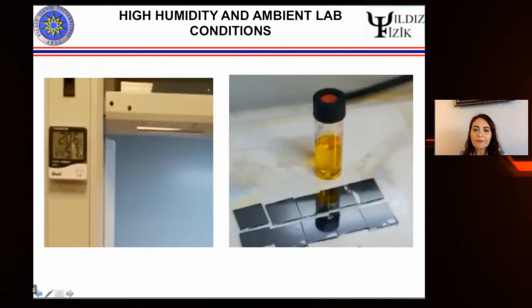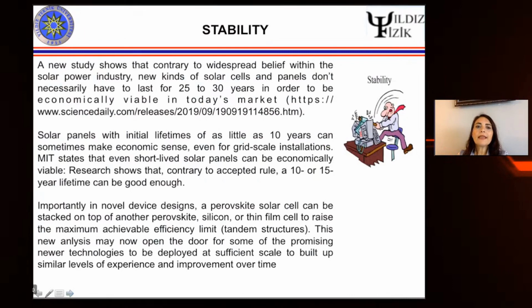So you see, in the previous talk, we also heard about these shiny, mirror-like perovskite layers, and this is high humidity conditions, and this is ambient lab condition, and these are our perovskites. What about the stability? Yes, stability is an issue, but there was a study like this. It was trying to say that people are expecting 25 years of lifetime, because this was the one which was provided by the silicon solar cell technology. So we have to think about now, for the new product to go into the PV market, is 25 years really necessary, or can we decrease it a little bit to 10 years? And this study actually gives us an answer on that. Maybe it's possible.